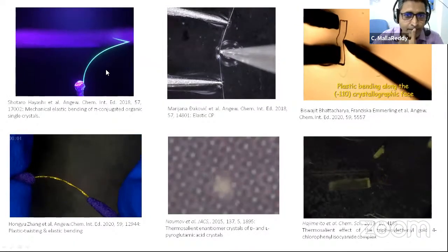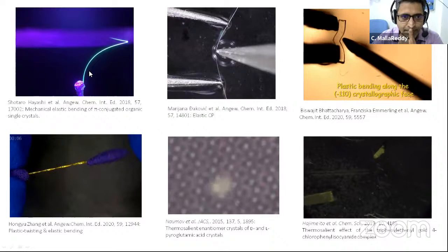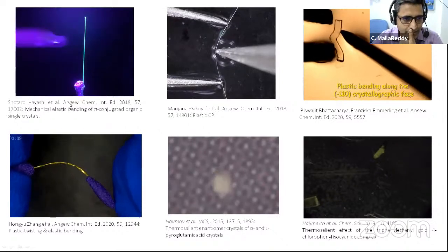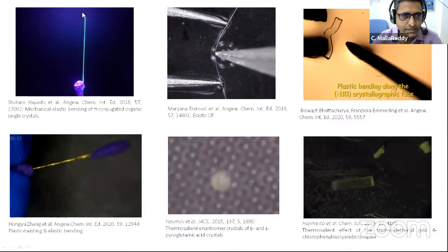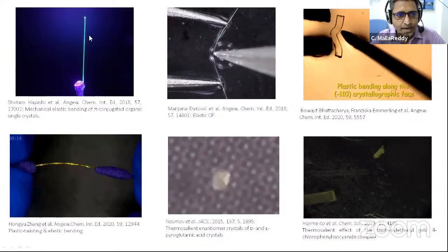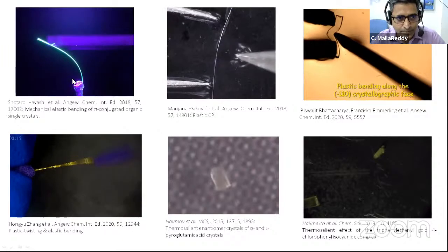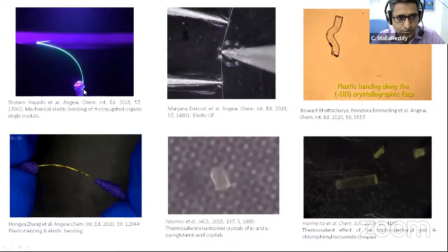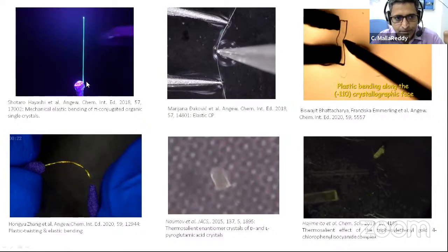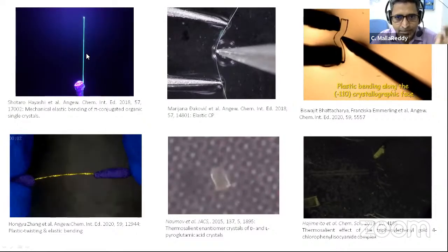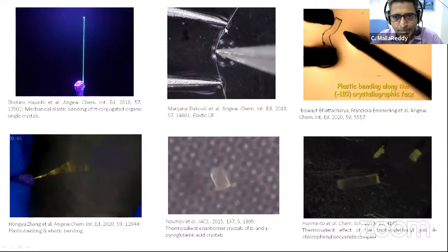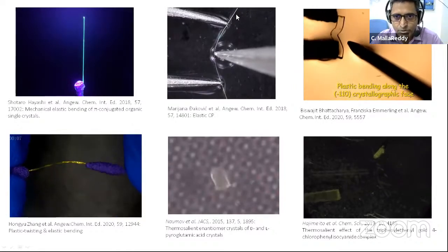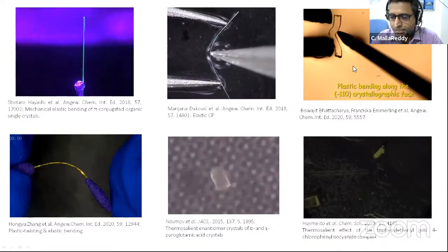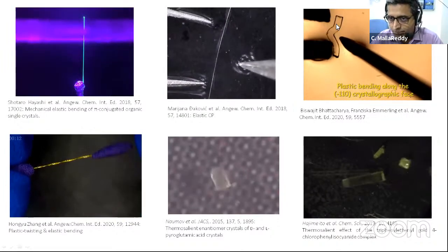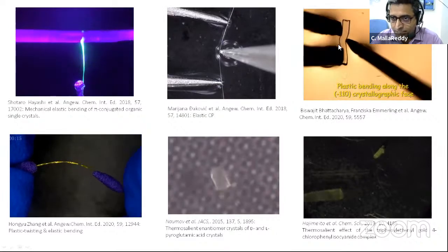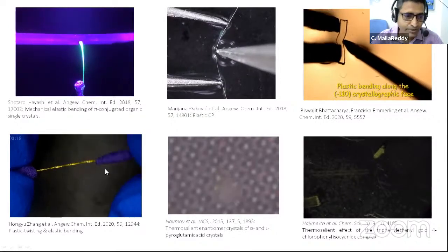Several groups have started working on elastic crystals, and a Japanese group has shown fluorescence in an elastically bendable crystal, and they have even studied the photophysical properties. I'm not covering it here, but they have shown the difference in the emission peak on the inner side and outer side. And this is a coordination complex; even metal organic complexes show elastic bending. Here again, this is a metal complex, and what you see here is plastic bending. And here you could even twist the crystals.